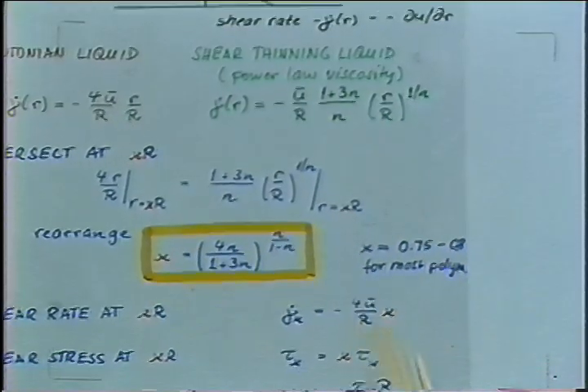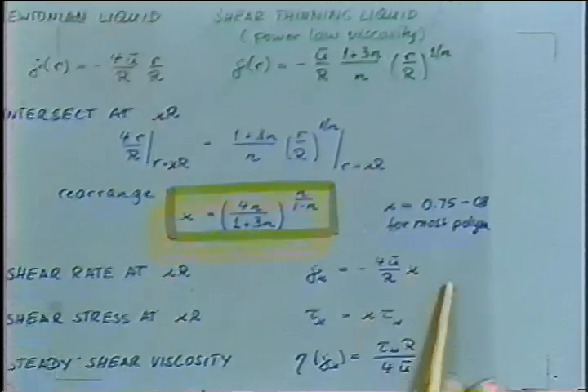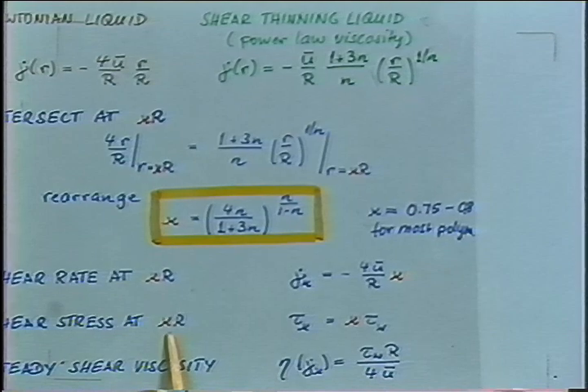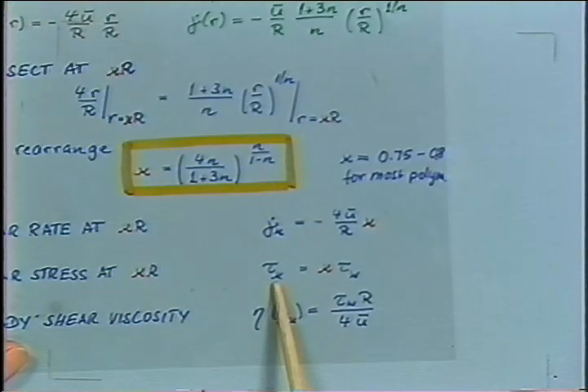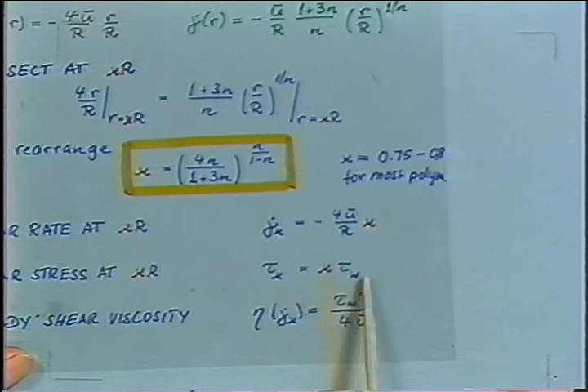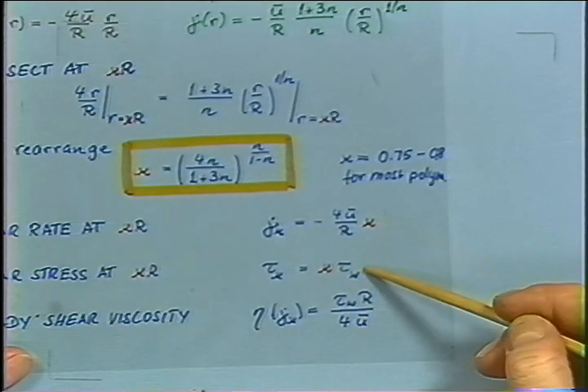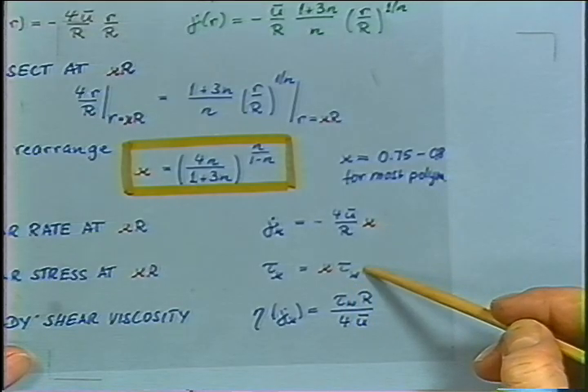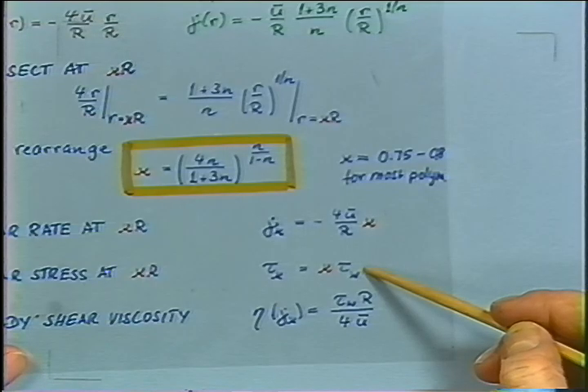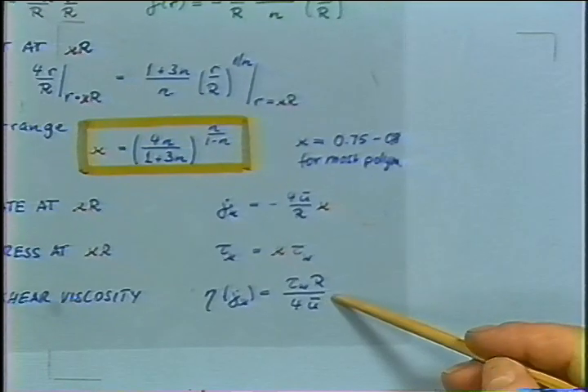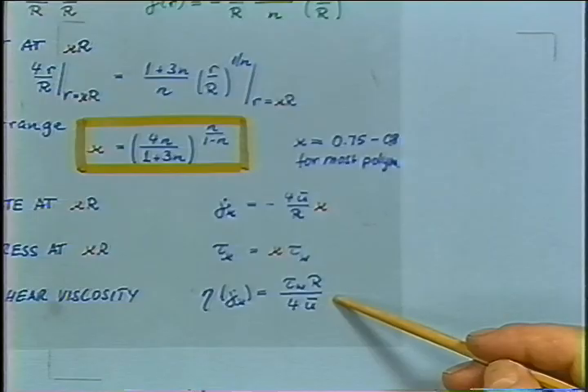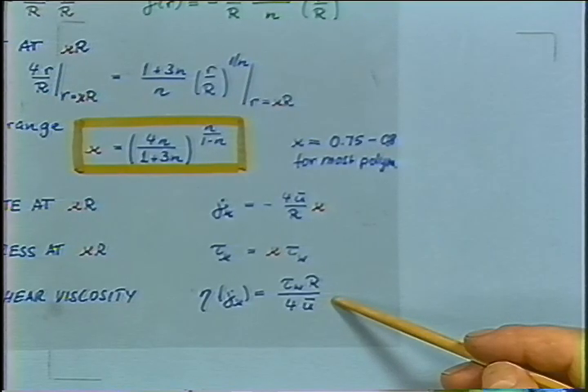It's just the Newtonian solution times kappa r. And the shear stress is given by the linear relation. You're at the position where you want to evaluate the shear stress, and you get that the shear stress is just kappa times the shear stress at the wall. So now you have shear rate and shear stress for this material element at some intermediate position, kappa, and you take the ratio, and you obtain your result. You obtain the viscosity which you wanted to have.